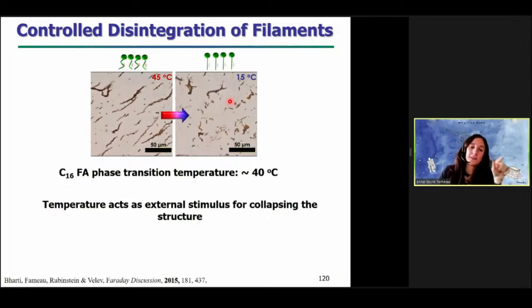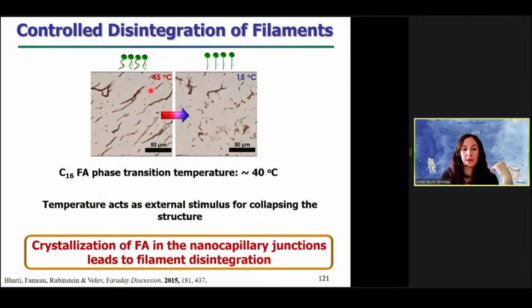And then if you increase the temperature again to 45 degrees and you apply the magnetic field again, you can recover your flexible filaments. So it's really this crystallization inside your nanocapillary junction that leads to the filament disintegration. So these nanocapillary bridges are responsive to temperature.